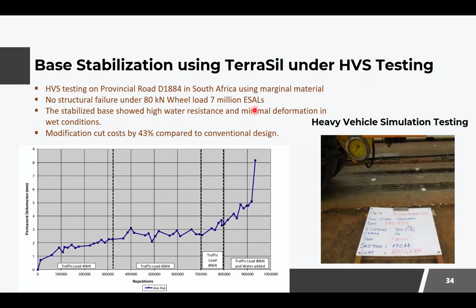ESAL cycles. And the results have indicated that the base stabilization showed higher water resistivity and minimal deformation in wet conditions. In South Africa, there was almost 43% cost reduction. This is because the testing was done on marginal material, and that's how we could achieve the economy. So these are a few results from the heavy vehicle simulations, as well as you can see the actual rutting that is happening.